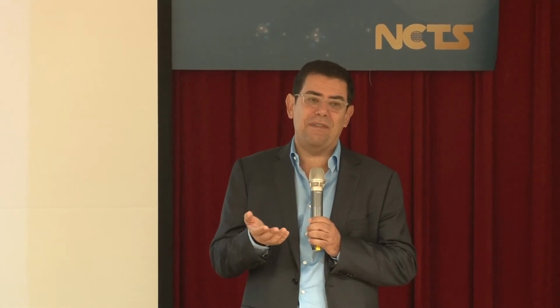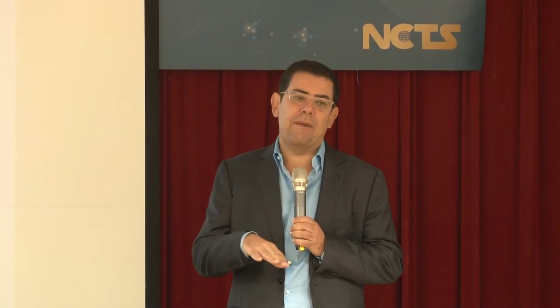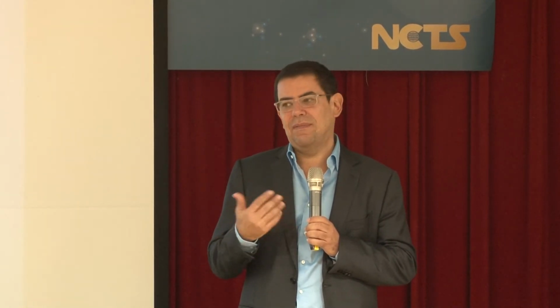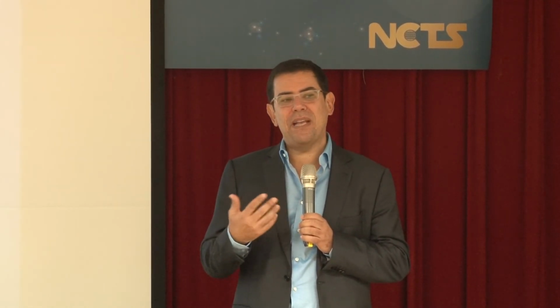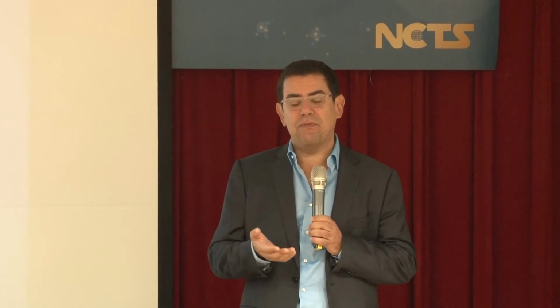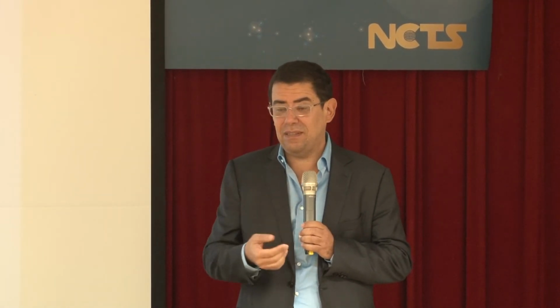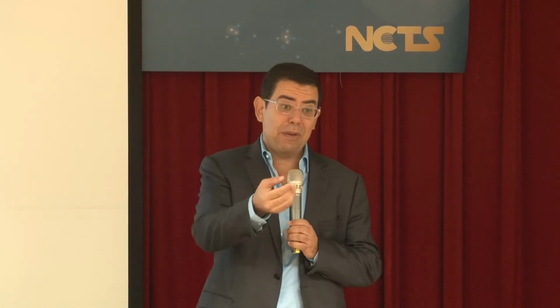But now the nice thing is that we already have these technologies. We can do this very fast. We just take this into the clean room in a glove box, and you exfoliate in the glove box, and you deposit boron nitride. It's like minutes to do. So the question is that for basic science, there is no point. But for industrial application, I think this has to be done, because to transfer this boron nitride in an industrial setting is not something easy to do, exactly because of mechanical limitations.